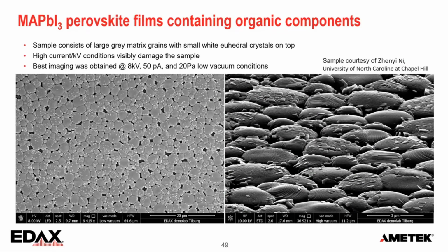Now, this is a project I worked on not so long ago. This was, again, a glassy matrix or substrate with a MAPI perovskite film on top. We have those larger gray crystals. These were the ones of interest. And when we tilt the sample, you see all these little white grains a little bit clearer. Those are small, probably lead iodide. We're not 100% sure what that is, because if I hit it with the beam, everything disintegrates. So I can't really identify where it comes from. For these images, I needed 8 kV, 50 picoamp, and low vacuum to keep this more or less stable.